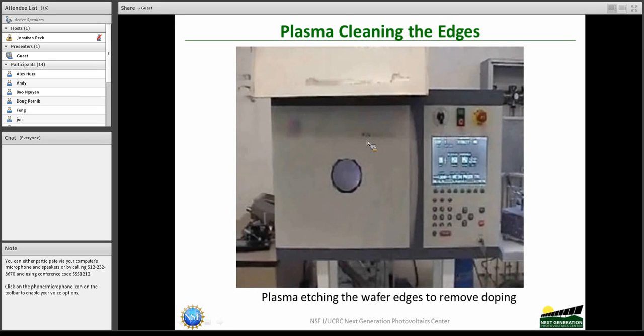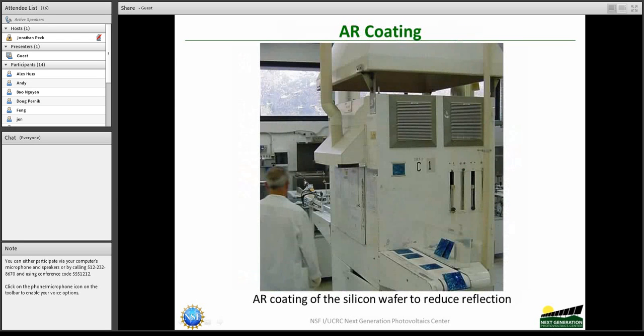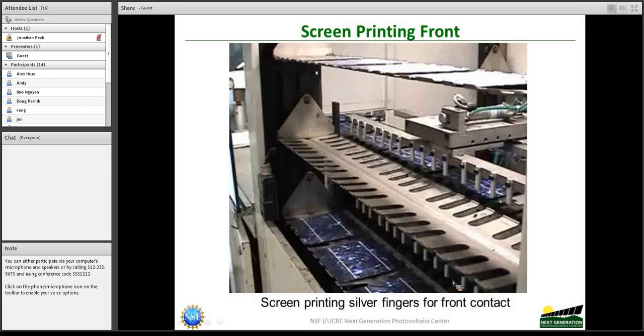And here is a plasma cleaning process to remove the doping that has happened on the edges of the wafer. The next step in making the cell involves coating with AR, and usually these coatings are silicon nitride-based coatings that reduce the reflection from the silicon surface. And this step is followed by screen printing the front, and you see some silver being screen printed on the front. This is what collects the current from the front surface.